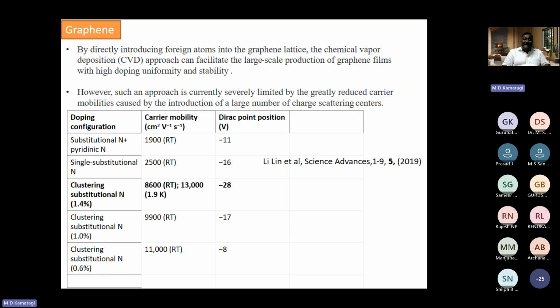Recently, there has been an interest in two-dimensional materials. Graphene is the first perfect two-dimensional structure, which is a single layer of graphite. It has a honeycomb structure, a hexagonal structure, where the carbon atoms are arranged in a hexagonal way. And we all know that graphene has a very high electrical conductivity and thermal conductivity. By directly introducing foreign atoms through a chemical vapor deposition, a CVD approach, we can produce graphene films with high doping uniformity and stability.